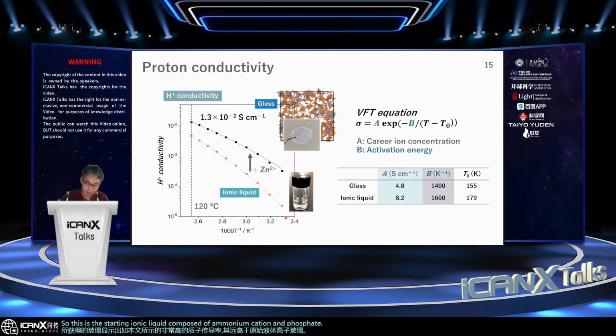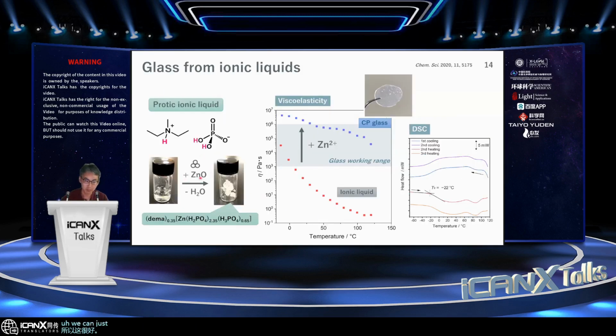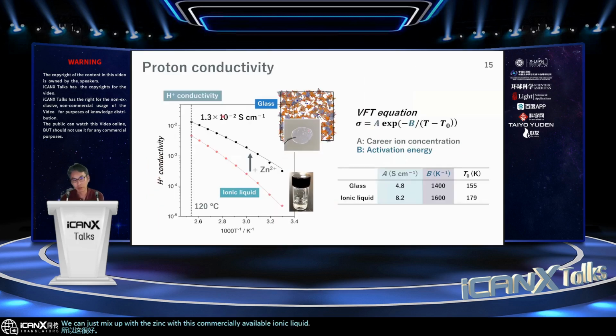So this x-axis is the inverse temperature, and this y-axis is conductivity. And if a sample shows proton conductivity in the range of 10 to the power minus 2 or 10 to the power minus 3, we can think of real application. But after reacting with zinc, the proton conductivity is really enhanced like this with solid state formation. So this is good because we can just mix zinc with this commercially available ionic liquid to form a very good proton conductor for fuel cells.